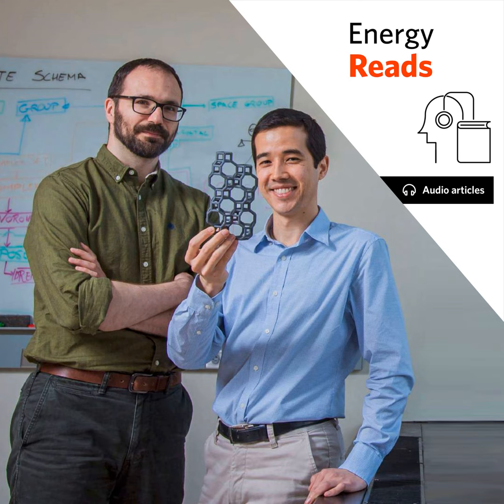Schwalbe-Coda describes another experiment that demonstrates the importance of molecular shape, as well as the types of new materials made possible using the team's approach. In one striking example, the team designed a templating molecule with a height and width that's halfway between those of two molecules that are now commonly used, one for making chabazite and the other for making a zeolite called AEI. Every new zeolite structure is examined by the International Zeolite Association and, once approved, receives a 3-letter designation.